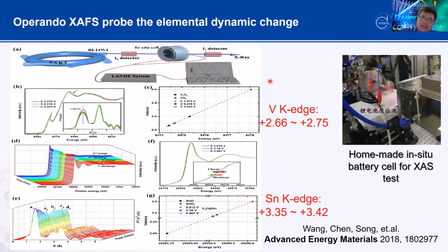And as you can see, if you look at the vanadium K-edge, you will see the average valence can change from 2.66 to 2.75. That means during the lithium storage, the vanadium really contributes. So this vanadium is an intercalated atom, but it really contributes to the lithium storage. But meanwhile, sorry, this is the host material.